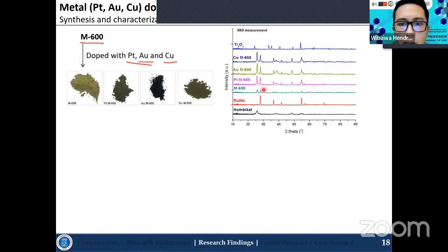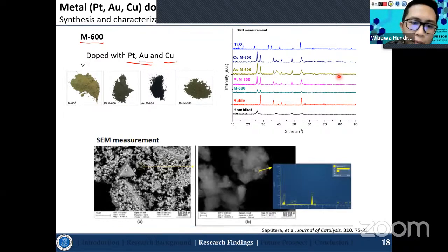There is no actual difference for the XRD patterns, because the size of the metals is very small, so it can't be detected by using the XRD, but it can be detected by using the SEM, where there are small dots in here, indicating the presence of platinum on the TiO2 surfaces, which means that the metallic platinum is successfully synthesized on the TiO2 composite nanoparticles.